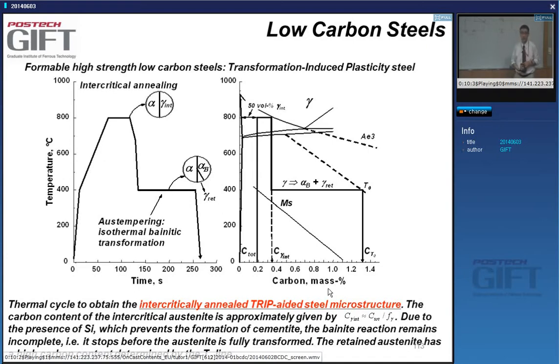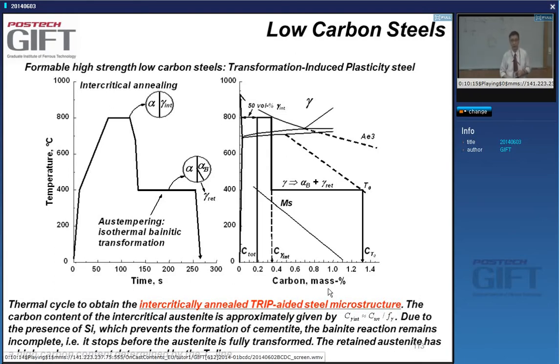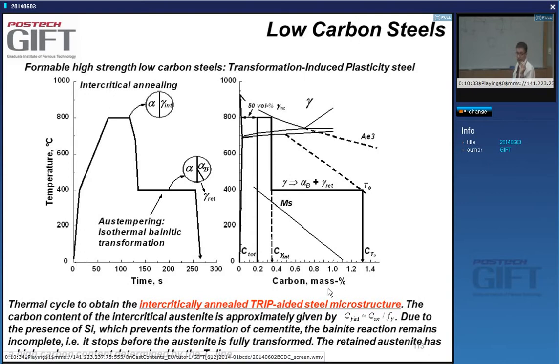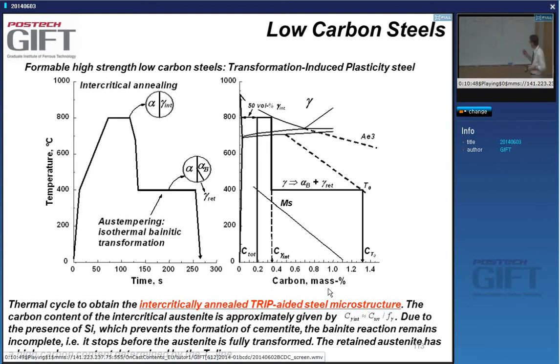At this stage we can see that the free energy of gamma is larger than the free energy of ferrite. So if I have this gamma phase, I will start to make ferrite. It's at low temperatures, so the transformation happens as a bainite transformation — it works in little steps. You form small units, and because they're ferrite — similar to martensite but in finer, smaller units — when I make this unit there is strain energy and it kind of stops.